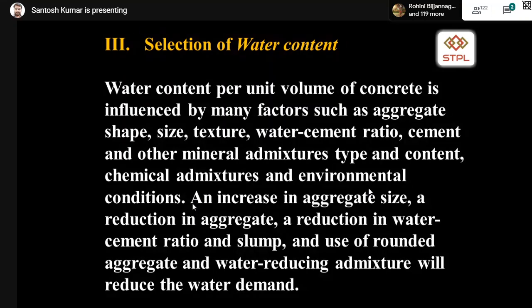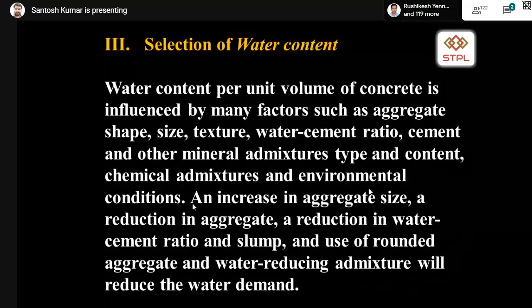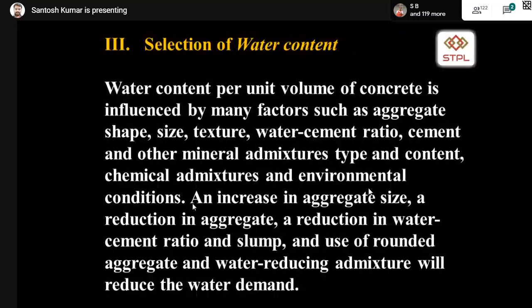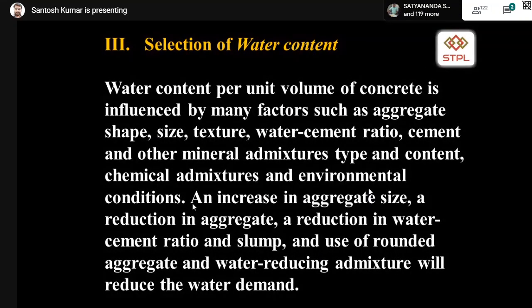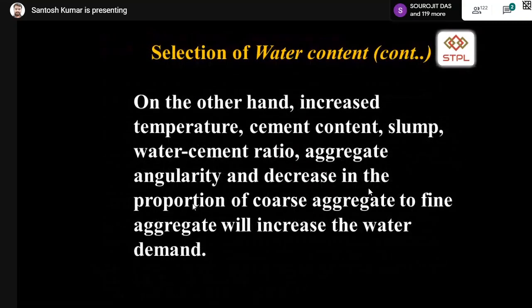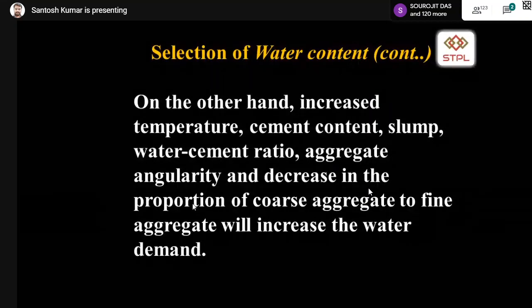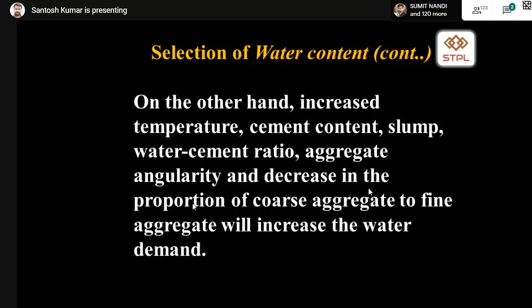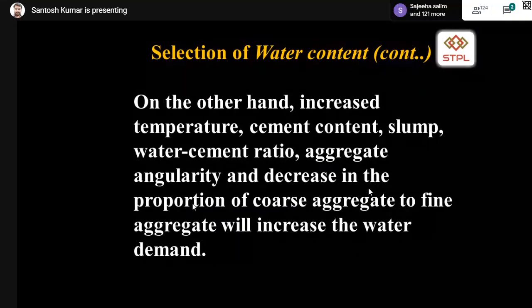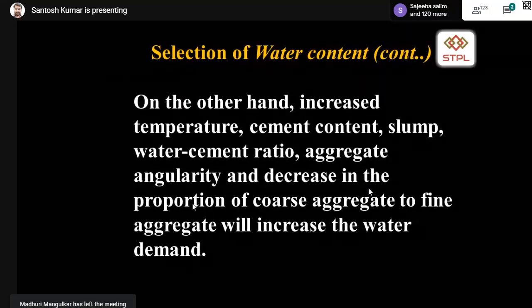Now, selection of water content. Water content per unit volume of concrete is influenced by many factors such as aggregate shape, size, texture, water cement ratio, cement and other mineral admixtures type and content, chemical admixtures, and environmental conditions. An increase in aggregate size, a reduction in water cement ratio and slump, and use of rounded aggregates and water reducing admixture will reduce the water demand. On the other hand, increased temperature, higher cement content, higher slump requirement, higher water cement ratio, aggregate angularity, and decrease in proportion of coarse aggregate to fine aggregate will increase the water demand.